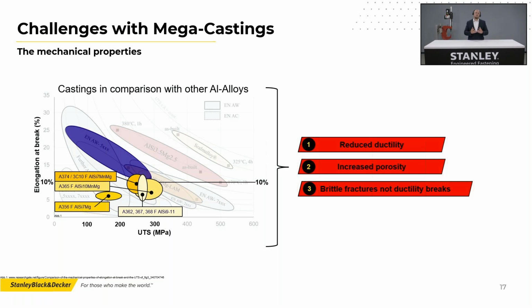A ductile crack means that the material is stretching, and you can see it stretching, and at some point it gets thinner like a rubber and then breaks. It's more like a spontaneous crack, because if you try to bend and deform this material, it's more like glass. If you want to bend and deform glass without making it hot, for example, it just breaks and shatters. So it's the same with these materials.